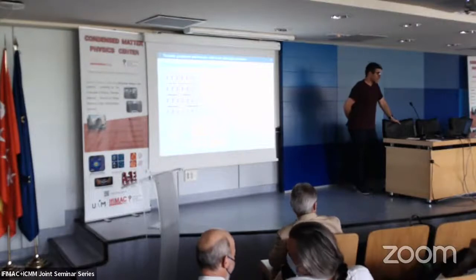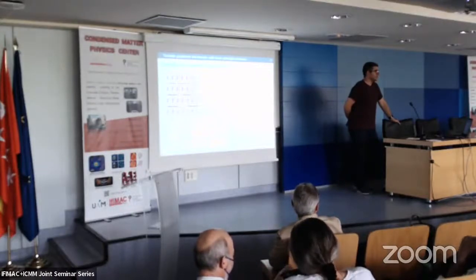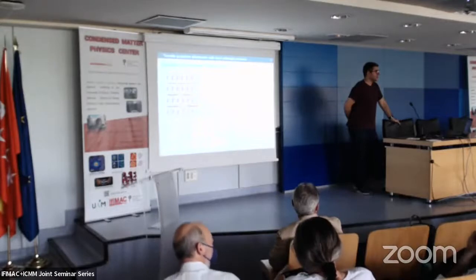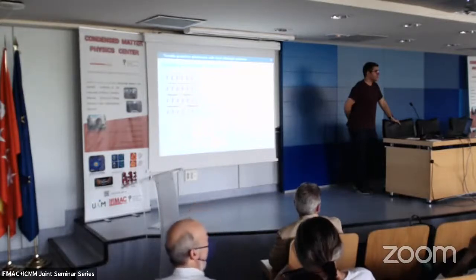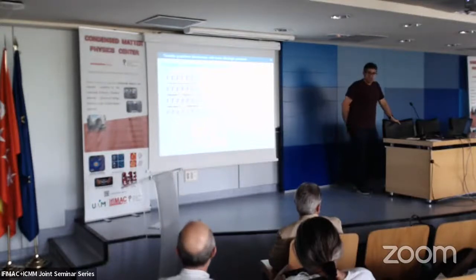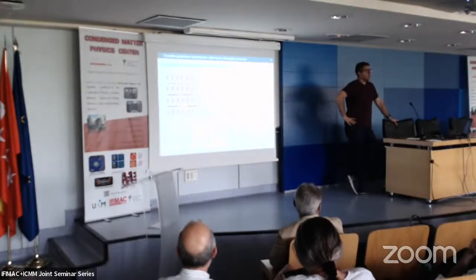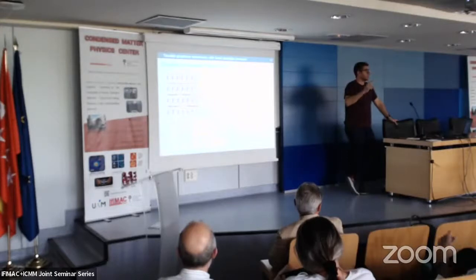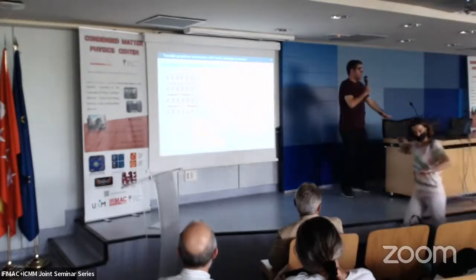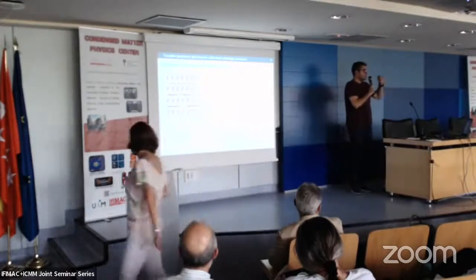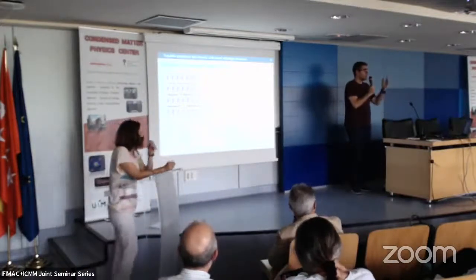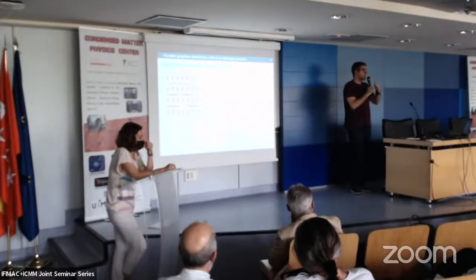Okay, thank you, Pablo, for the talk. I don't know if you are concerned about the latest work from Elisa Riedo, who said that they achieved this kind of diamond-like configuration with bilayer graphene, and it actually grows. It's the reference I placed, but if you see the data, there are two sets of data. One of them I think is more okay: they study indentation, they see the stiffness in the indentations. They study different numbers of layers, and for example, with one layer or 5 layers, they don't see this stiffening, but for, I think, 2 layers, they see how it stiffens.